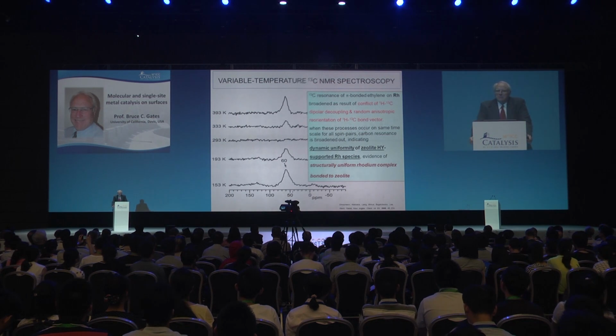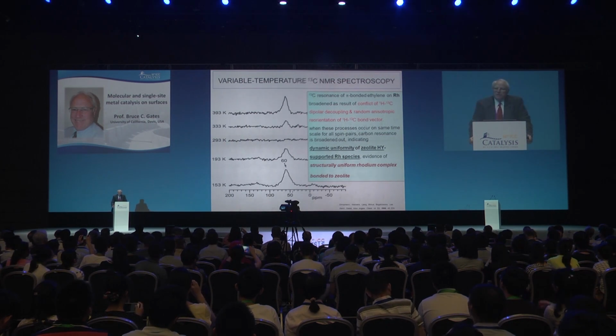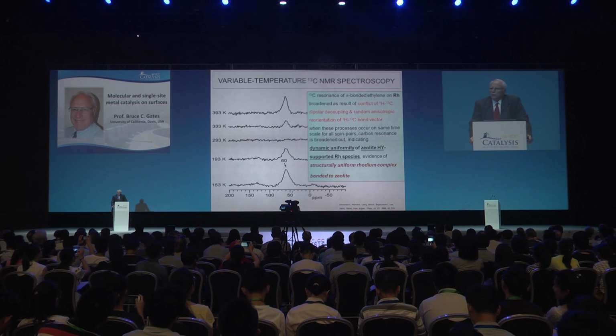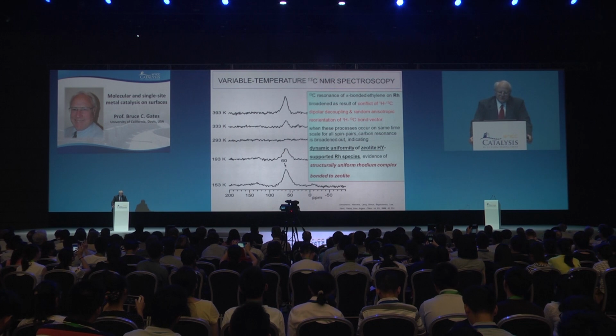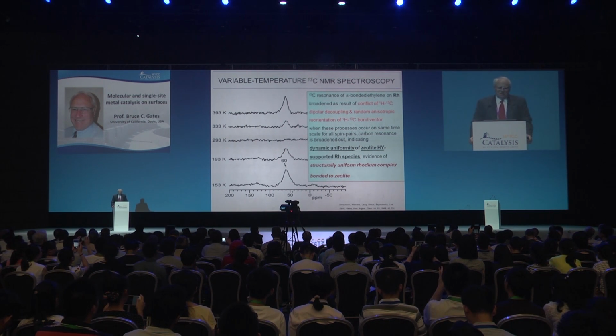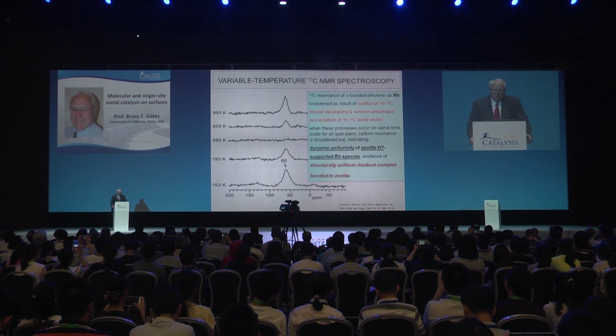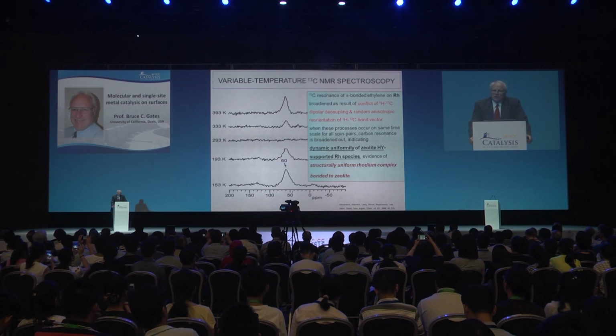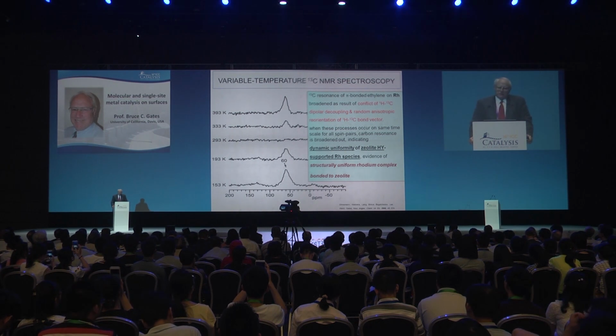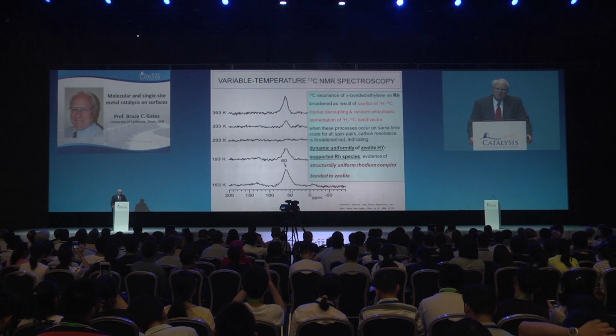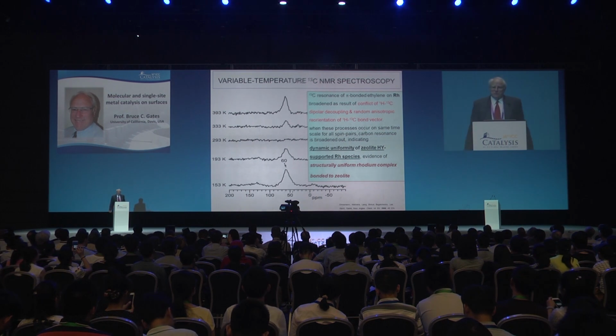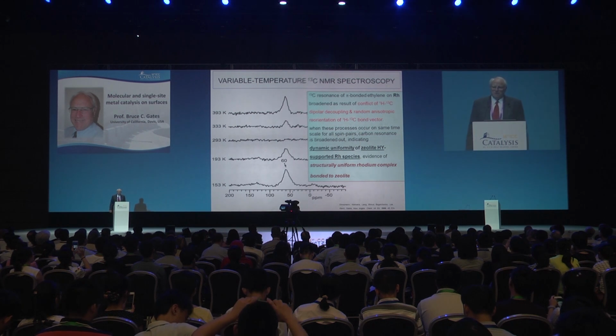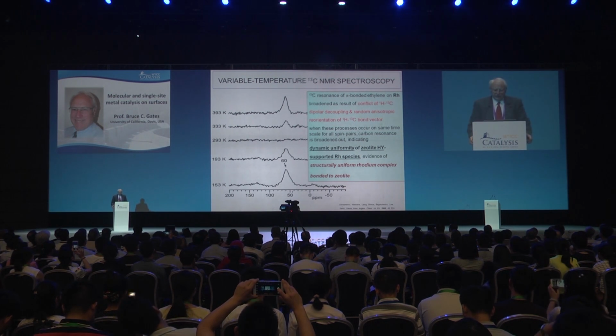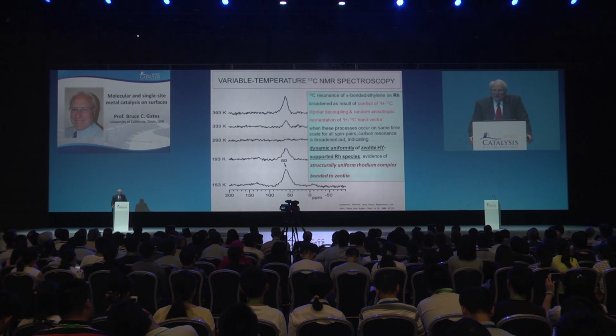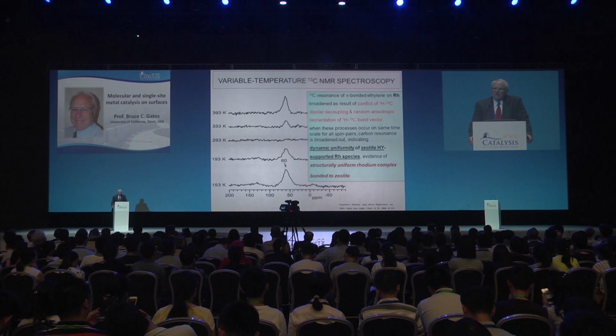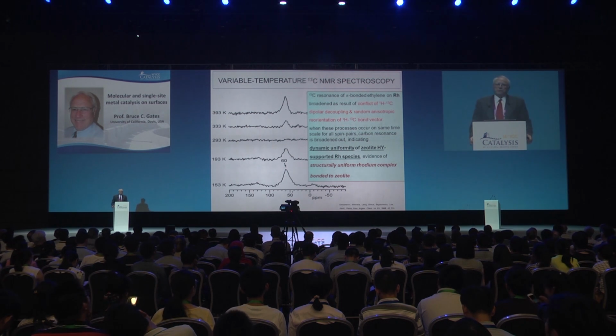NMR is valuable in this respect. Here we've got the zeolite-supported rhodium diethylene complex enriched in carbon-13. Running the temperature from high to low leads to a broadening of that band in the spectrum. Raising the temperature from low to high gets us, at the same temperature, to a fully broadened band resonance. That's indicative of dynamic uniformity around the carbon-13, and from that we infer structural uniformity of the supported species.